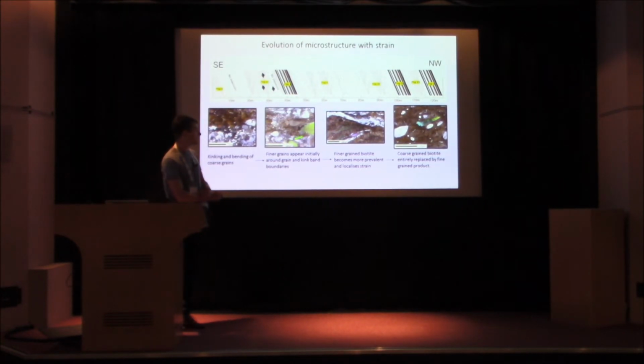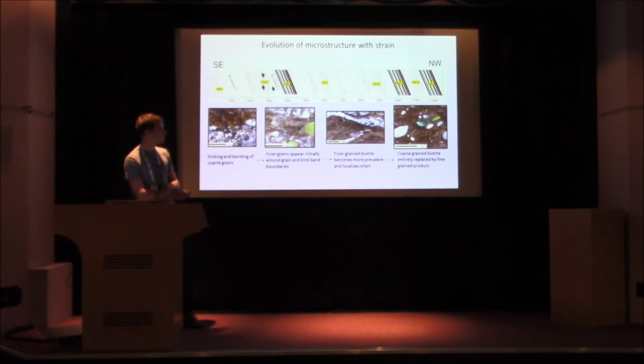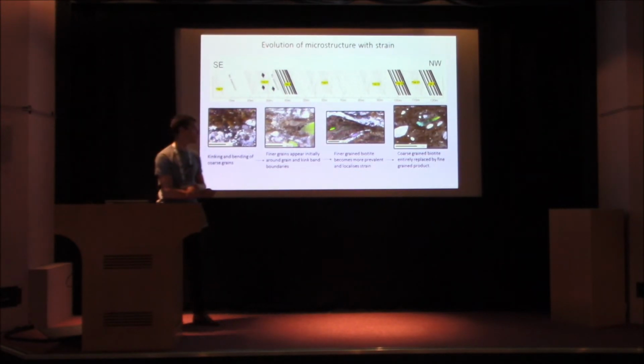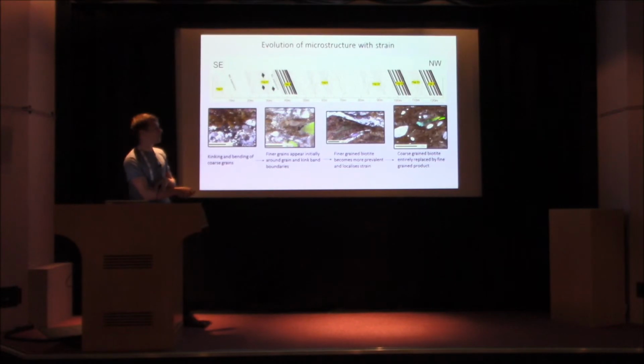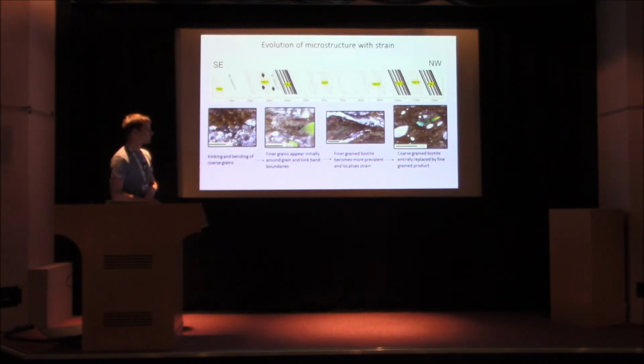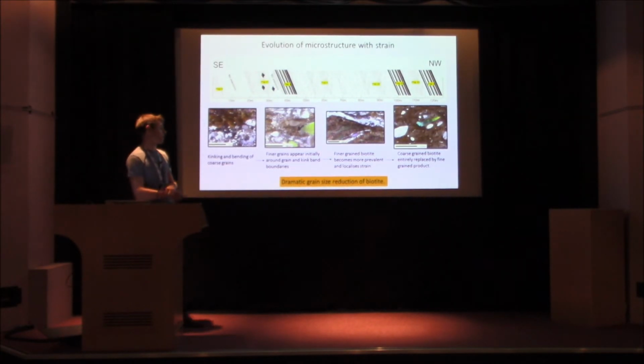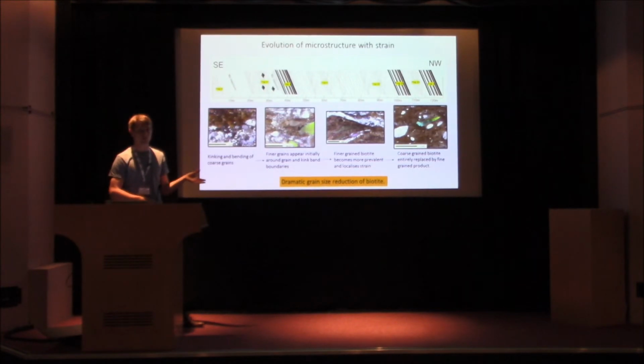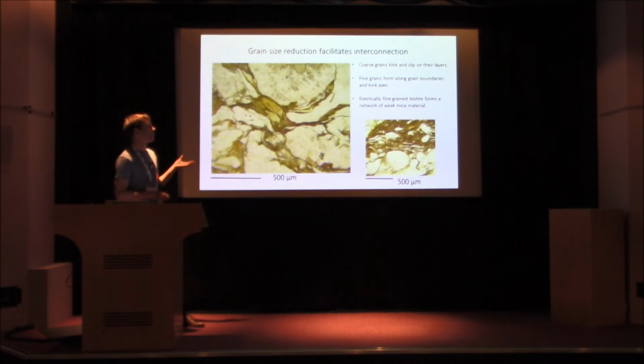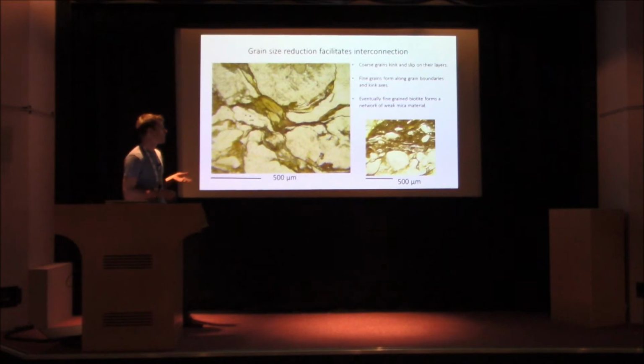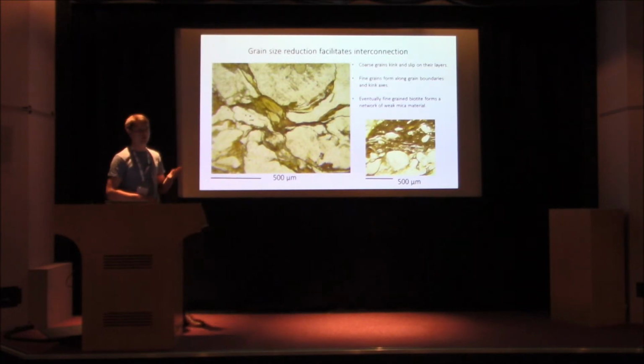And as you increase in strain here, this is a coarse grain, but all of this around here is very fine-grained material. And you can see how the lighter stuff is not deforming as much, but the finer-grained material is taking on a lot of the strain, until finally you get to darker, much finer-grained material forming a matrix that forms the majority of the rock. So clearly there's a dramatic grain size reduction. But importantly, what's forming this grain size, this interconnection? What mechanism is allowing this grain size reduction to occur?